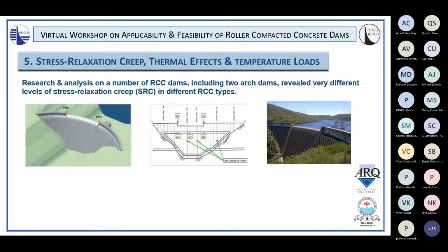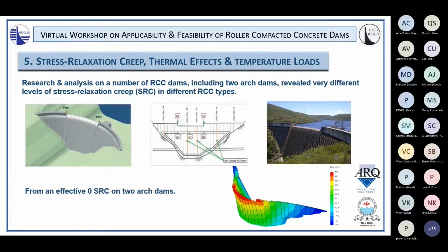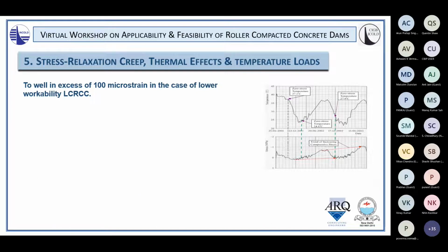So looking now at stress relaxation creep, thermal effects, and temperature loads, research and analysis on a number of RCC dams, including, importantly, 2 arch dams, revealed very different levels of stress relaxation creep in different RCC types. From an effective 0 stress relaxation creep on 2 arch dams, and notice the point effective 0, I'll explain that later, to well in excess of 100 microstrain in the case of lower workability, low cementitious RCC. And this is particularly relevant because this RCC might have had an adiabatic hydration temperature rise of the order of 7 to 8 degrees. So in fact, even more than the temperature equivalent of the hydration temperature rise was seen in the stress relaxation creep in this particular low strength RCC type.